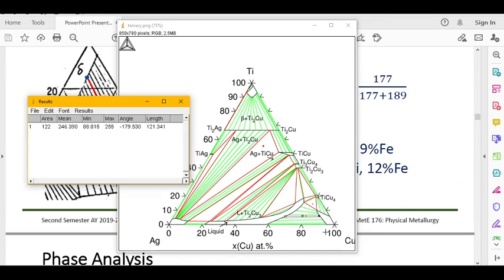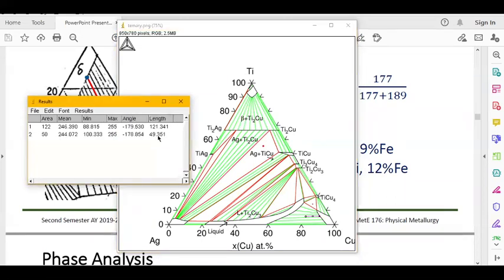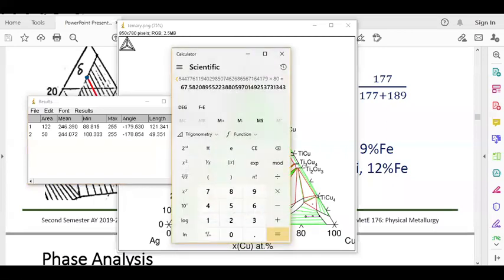So, if I were to get the amounts of phases in my mixture dito sa two-phase region na to, then I will just use the inverse lever rule, no? So, for example, if I want to get liquid, then I just readjust this, parang ganyan. Press M, measure. So, that's 49.351. So, 49.3 divided by 121.34 gives me 40%. So that's 0.406. So let's just say 41%.